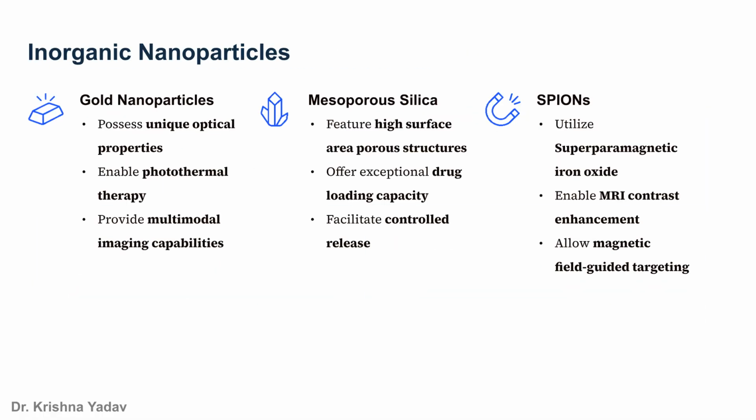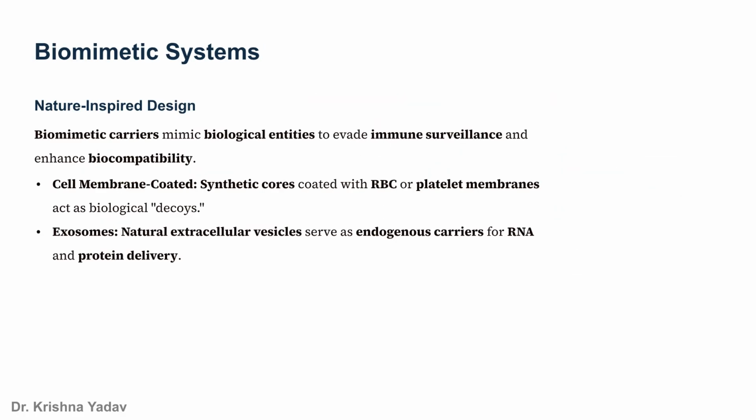Inorganic nanoparticles are also highly promising. Gold nanoparticles enable photothermal therapy and multimodal imaging. Mesoporous silica offers high drug loading capacity and controlled release. SPIONs, or superparamagnetic iron oxide nanoparticles, are used for MRI contrast and magnetic field-guided targeting. Biomimetic systems mimic natural entities to evade the immune system and enhance biocompatibility. Examples include cell membrane-coated carriers, which use red blood cell or platelet membranes as decoys, and exosomes, which are natural endogenous carriers for delivering therapeutic molecules.